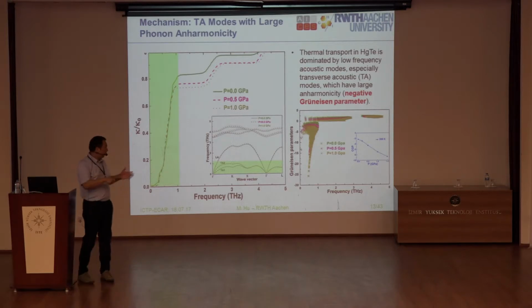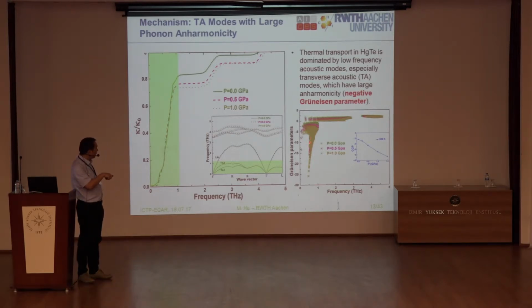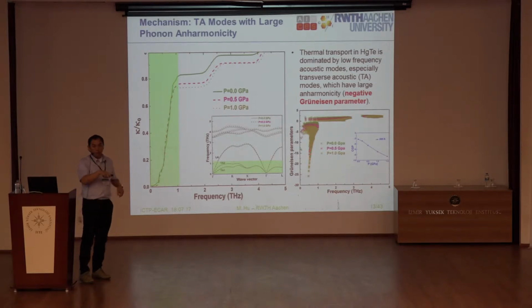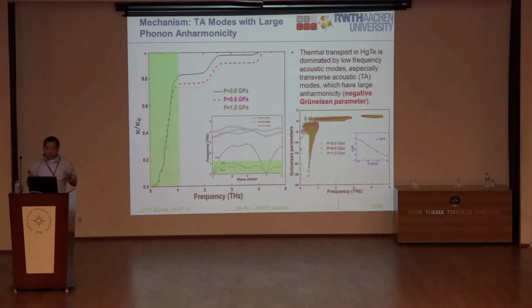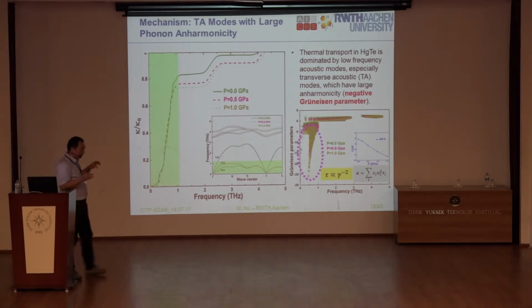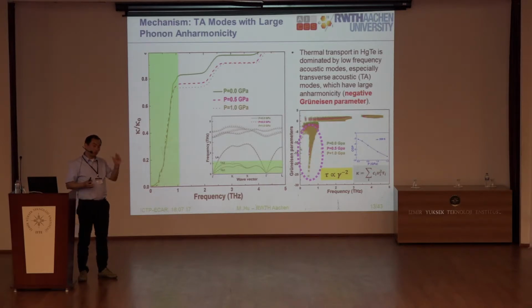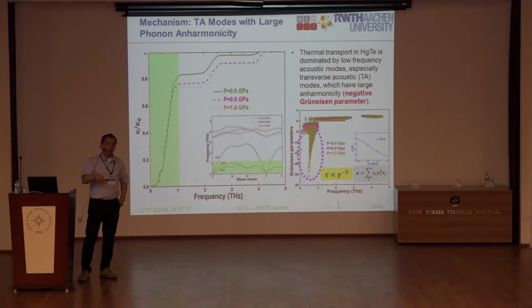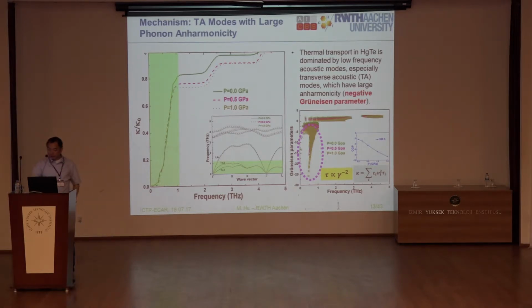Once you apply the pressure, this negative Grüneisen parameter actually goes even further in the negative direction. It means the magnitude of the Grüneisen parameter becomes larger, which means the phonon anharmonicity becomes higher, and of course you then have this very low thermal conductivity, right? Because tau is inversely proportional to the magnitude of the Grüneisen parameter. So now we found the reason: for such a special material, if the transverse acoustic modes dominate the phonon transport, and the negative Grüneisen parameter of such modes continuously decreases under pressure, then you will have this negative pressure dependence in the thermal conductivity.